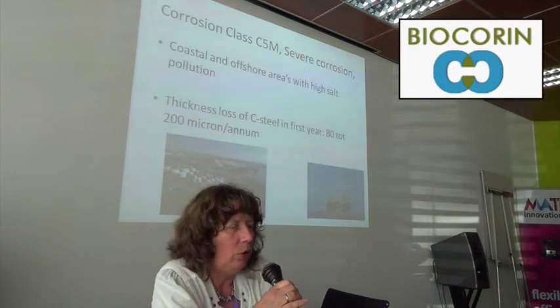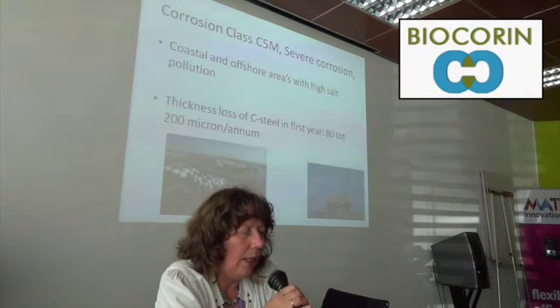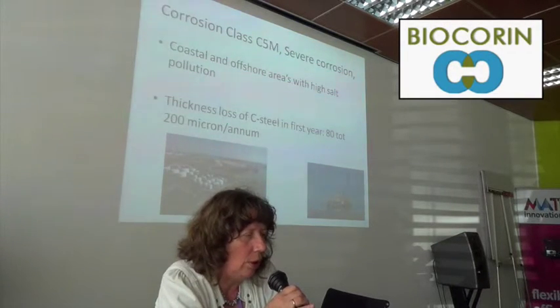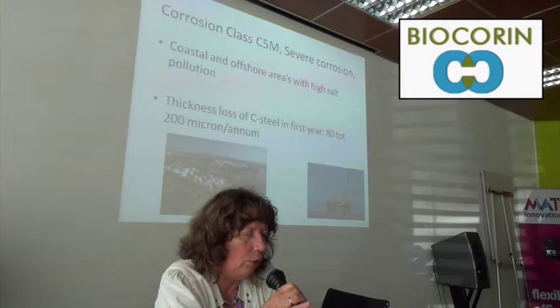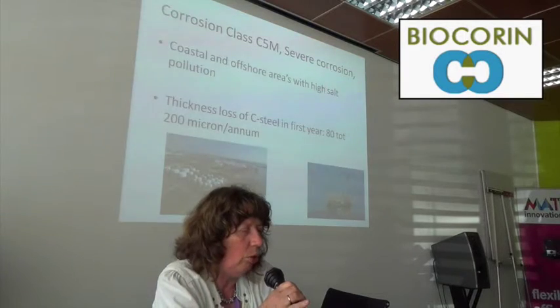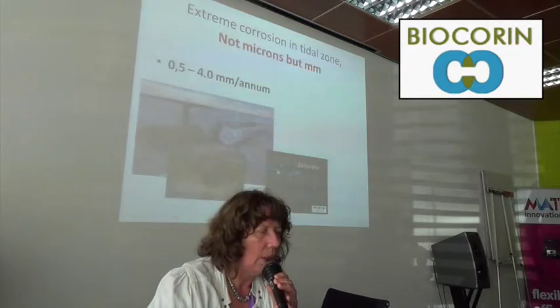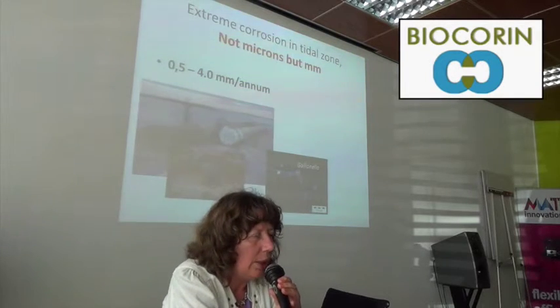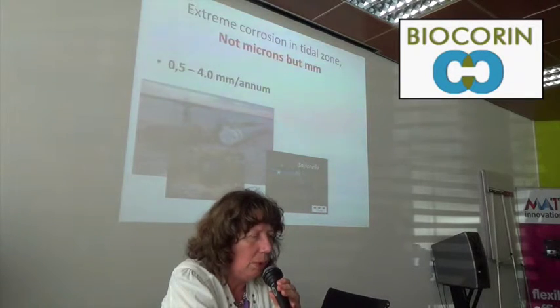One of the most severe corrosion takes place in the coastal and offshore areas with high salt pollution. This is called corrosion class C5M. On average, the loss of carbon steel in the first year is 80 to 200 microns per annum. However, there is extreme corrosion in the tidal zone — not in microns, but in millimeters.